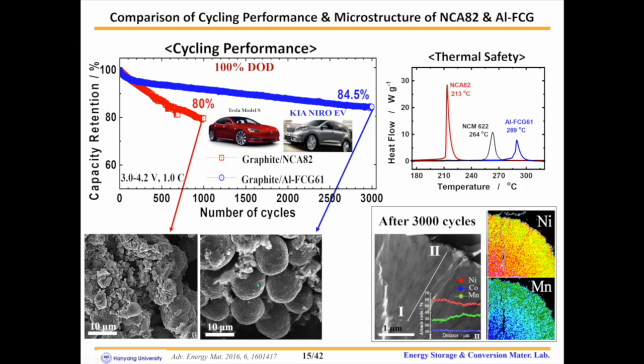As you can see from the same image, nearly all of the particles from the cycled NCA cathode were completely pulverized. In comparison, in the cycled FCG cathode, the original spherical morphology was well preserved. In addition, composition line scan confirms that the original concentration gradient was well maintained even after 3,000 cycles.